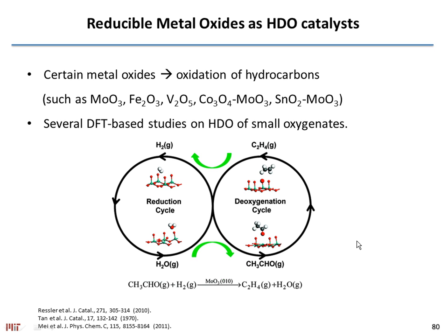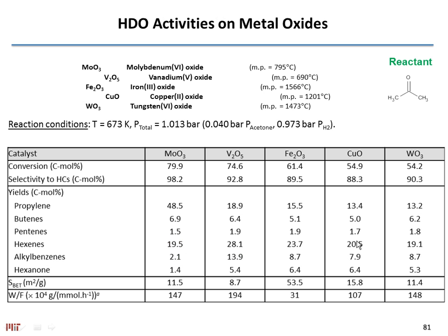In this case, we would want to operate in reverse, where we create oxygen vacancies on our oxide, and then let the oxygenate land on the surface, and then use hydrogen to do a hydrogenolysis reaction over there, and then regenerate that vacancy with hydrogen again. So it would be kind of like a stepwise dehydration reaction. So, we did an initial screening with different types of oxidation-based catalysts, right?